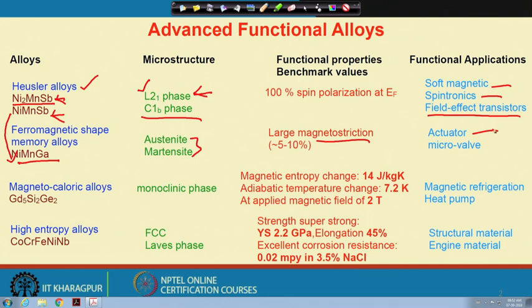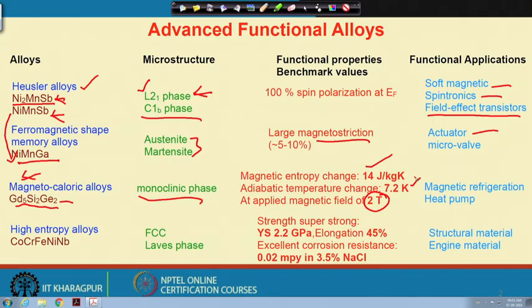Now, the third type of material, these are also magnetic materials. However, in those magnetic alloys, as an example, we may have some monoclinic type of structures. This is a gadolinium compound, gadolinium silicon germanium. The interesting phenomenon here is that by application of a magnetic field, let us say a value in the range of 2 Tesla, we can achieve a large magnetic entropy change in the order of 10-14 joule per kg Kelvin, and that simply changes the adiabatic temperature of the material in the order of 7.2 Kelvin.